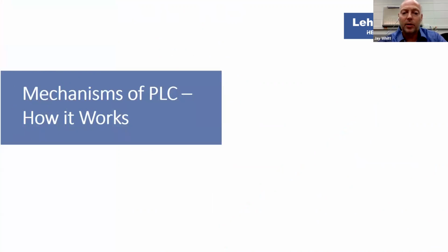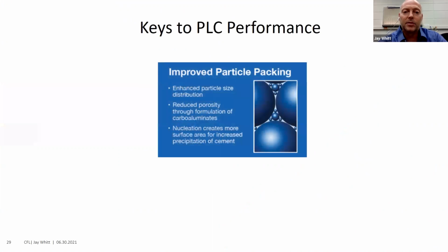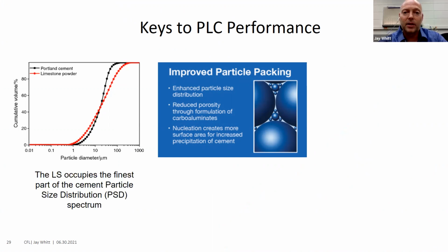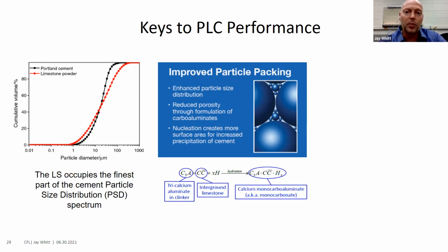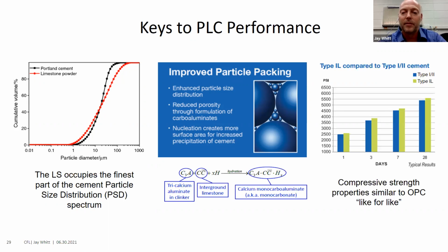And how do we do this? There's basically 3 mechanisms that we look towards. One is particle size. The other 2 are based upon chemistry and how the interaction happens at that micro level. From particle size, it's real easy to get caught up in this, but limestone is a little bit easier to grind and allows for greater distribution, which greatly helps not only with the finish from a physical point of view, but also from a chemistry point of view. From a chemistry point of view, we can get really into detail, but the carboaluminates are going to help with the hydration of that cement.